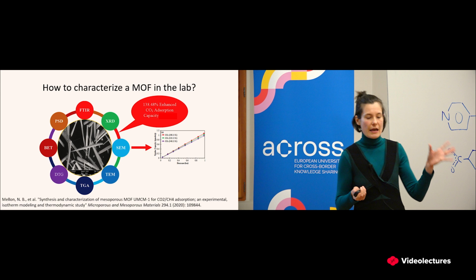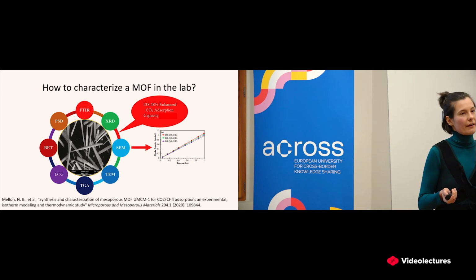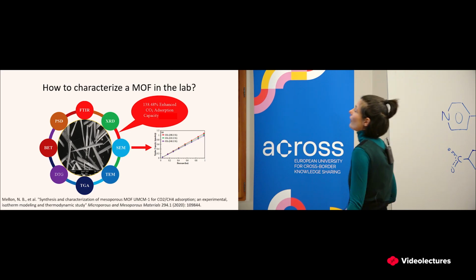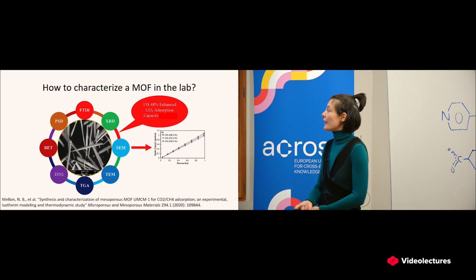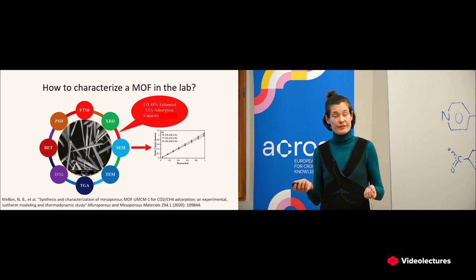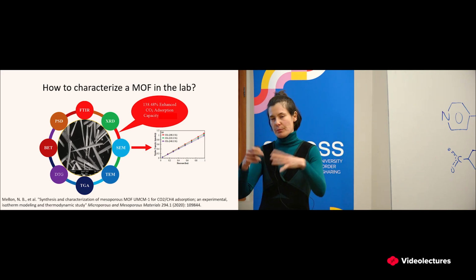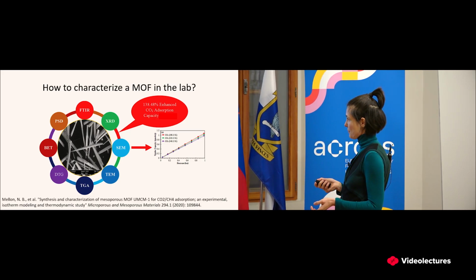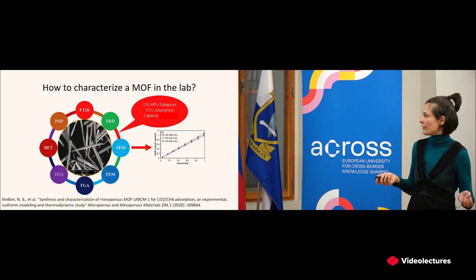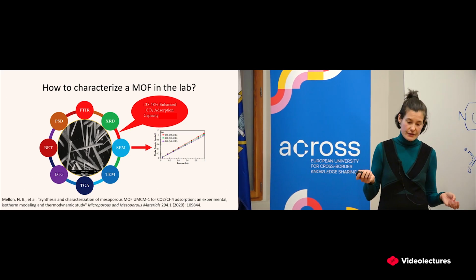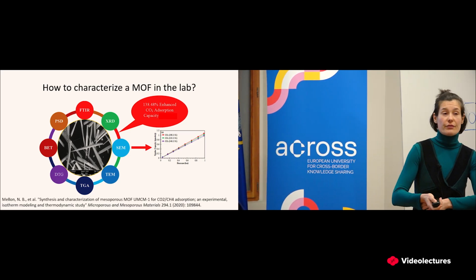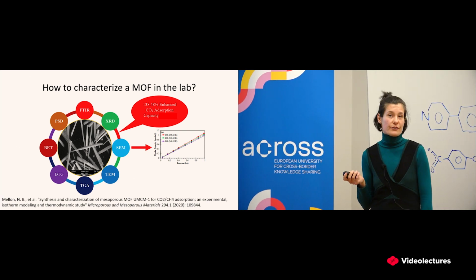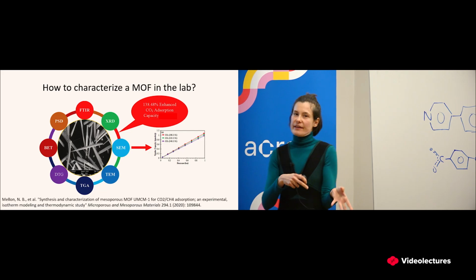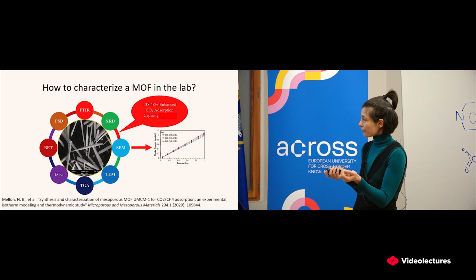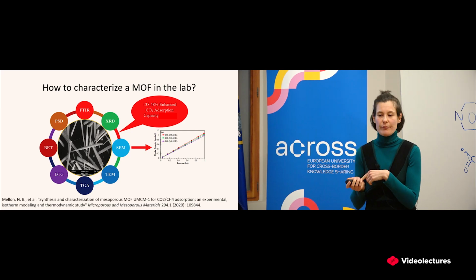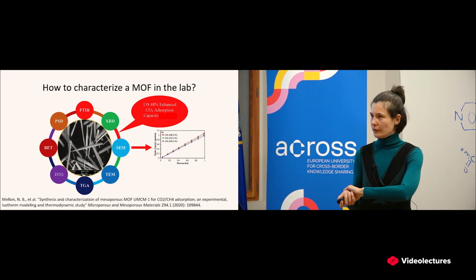So after you have synthesized and purified your MOFs, then you also have to characterize them. And there's a whole range of different techniques that we use to do that. So, of course, porosity is very important, so it matters the surface area, the pore size distribution, etc. So you do gas adsorption measurements to characterize these MOFs in this way. Of course, you also do X-ray diffraction in order to then get the structures of the materials you have synthesized. We use infrared spectroscopy to see which functional groups have reacted, which ones have not, and so on. And then also thermal analysis with a thermogravimetric analysis setup. We see how thermally stable the materials are.